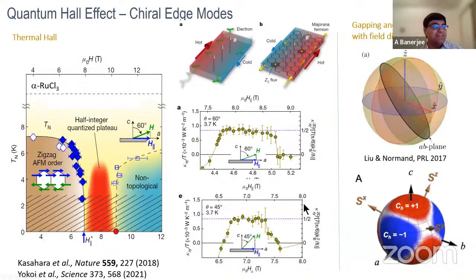And that was great. Not only that, there is this PRL paper by Bruce Normand, which showed that if you move the field in different directions, you should get a different Chern number. At different directions of the field, in some directions you would not get this plateau, while in other directions you will get the plateau, but the plateau will be at a value of minus half instead of half, corresponding to a Chern number of minus 1 or plus 1. And they were able to show that exactly as well. There was another paper, the Yokoi paper, published in Science in 2021, which showed that this really complies with the picture that we see here: if you apply the field in different directions in the sample, you really have control over the Chern number of the material.